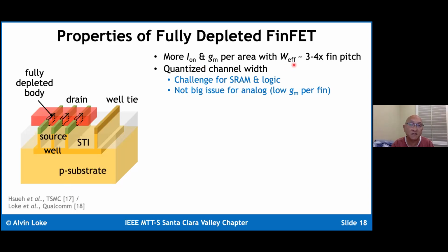Okay, simply because the effective width, which is basically the perimeter, or not quite perimeter, but basically twice the height of the active device fin plus the width of the fin. When you actually look at modern day transistors down to 5 nanometers, they're actually closer to 4 times the fin pitch. Okay, so what would have been normally your channel width on a planar scale, by wrapping things into the third dimension, you're actually getting 3 to 4 times effective gate area, or gate length. Gate width, I'm sorry. Okay, and so the channel width is quantized in chunks of the number of fins you're using.